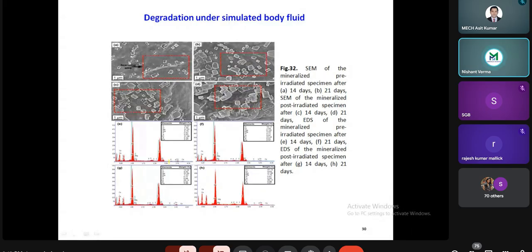So in order to find this, the material should be prone to formation of apatite crystal. So we have used the simulated body fluid, which is synthetic. We immersed the specimen in that fluid, and after a certain number of days, like 14 days and 21 days, we can see that the material has bone bonding ability.